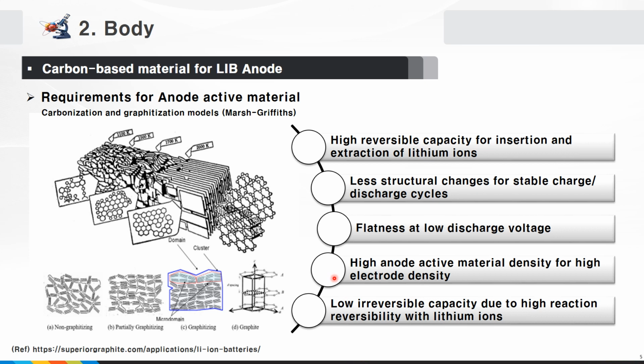Fourth, the density of the anode material must be high to obtain a high electrode density. Fifth, the reaction reversibility with the lithium ion is high, so the irreversible capacity should be low. The ideal reversible reaction has a charge-discharge efficiency of 100% and there is no change in the reaction efficiency with the cycle. As illustrated on the left,